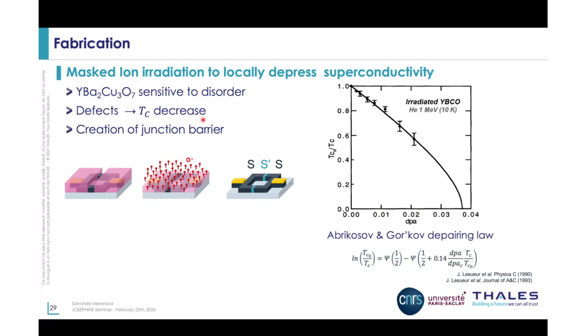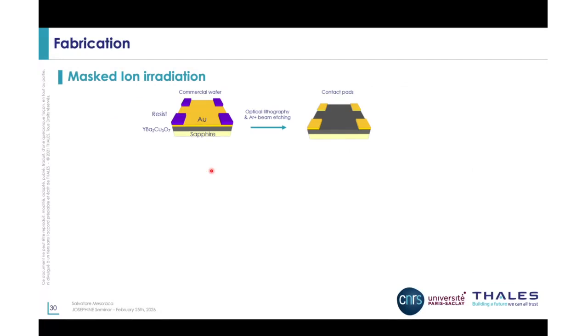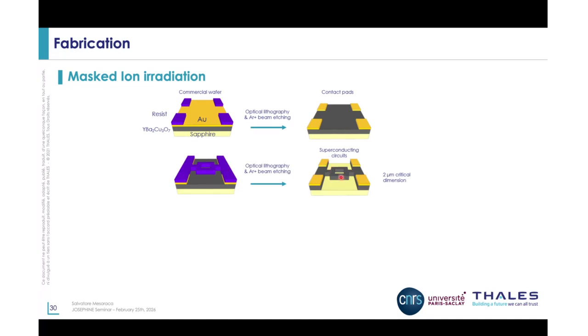So the way we make junctions is to protect our conducting loop, except for the area where we want to create the junctions, and irradiate with very high energy oxygen ions. So let's talk about how we do the fabrication in its entirety. We start with a commercial wafer, which is YBCO grown on sapphire and capped by a gold layer. The first step is just an optical lithography and an argon ion beam etching, just to define the contact pads. And in a similar fashion, we define the superconducting circuits. You can see here it's a superconducting loop.